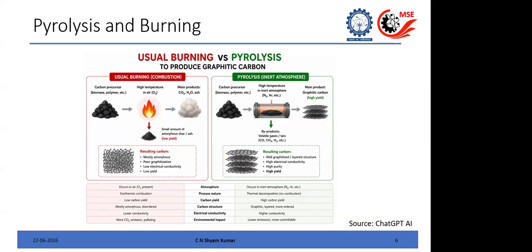And the yield is very low because you lose everything, because carbon and oxygen are very good friends. They make CO2, CO, and other volatiles will go if there is oxygen. So your yield is very low. But in the case of pyrolysis in an inert atmosphere or in a high vacuum, the carbon won't go as carbon dioxide or carbon monoxide because there is no oxygen.